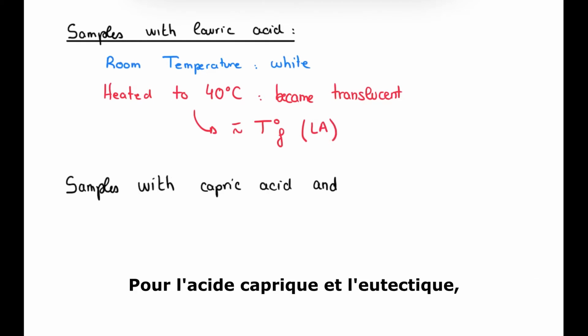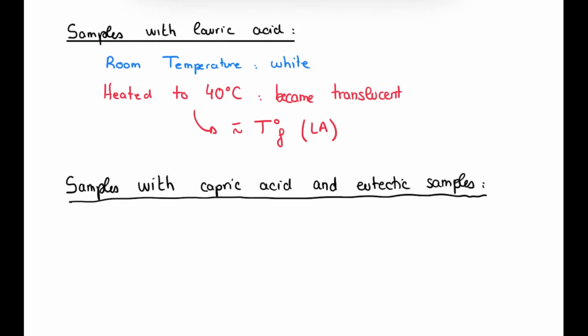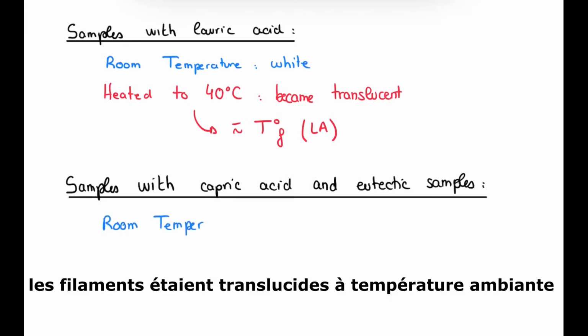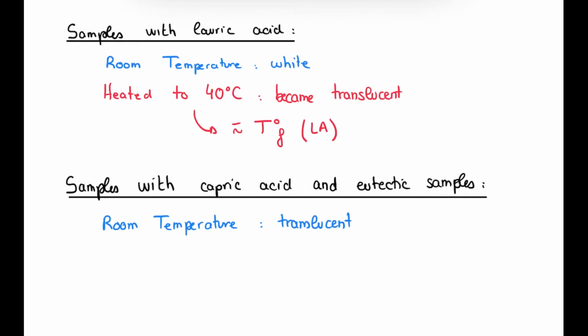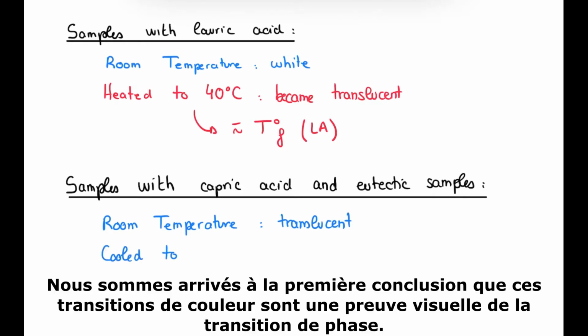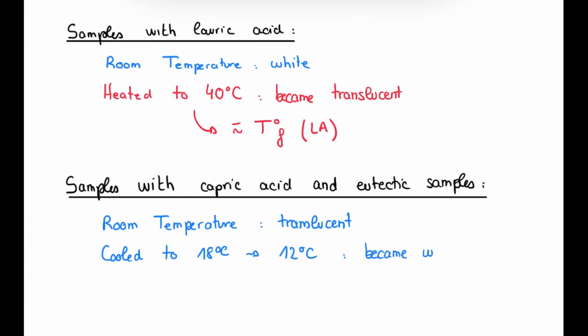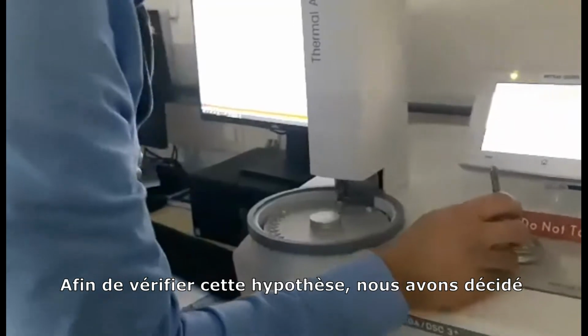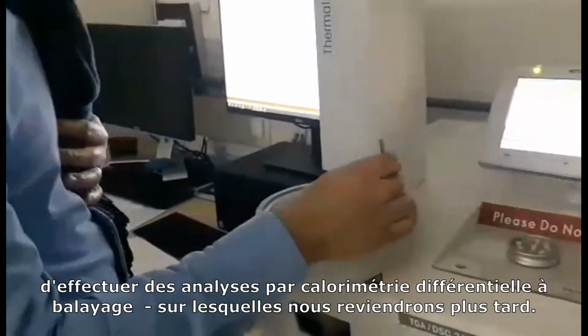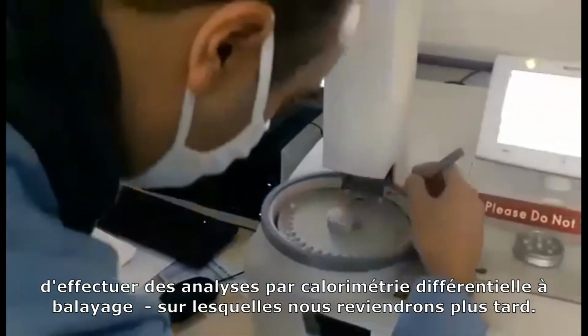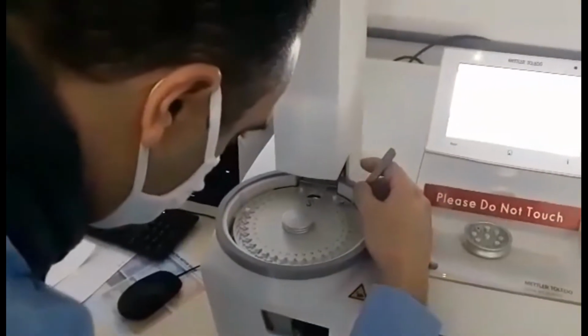For the capric acid and the eutectic samples, the filaments were translucent at room temperature and became white when cold. We came to the first conclusion that these color transitions were a visual proof of the phase transition. In order to verify this hypothesis, we decided on doing differential scanning calorimetry analysis, to which we'll come back later.